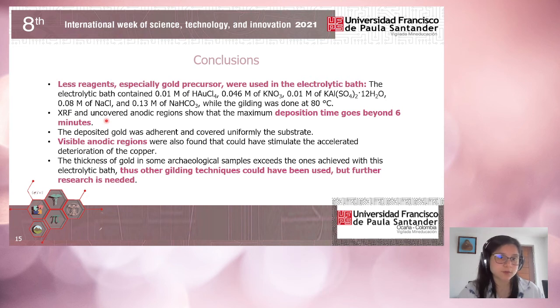XRF and uncovered anodic regions show that the maximum deposition time could have gone beyond the 6 minutes, taking into consideration that Heather Lechtman reported this thickness in about 5 minutes. The deposited gold covered the substrate uniformly. Therefore, we didn't go further into the annealing of the sample, even though we could have done that. And it's definitely something that perhaps in the future must be done.